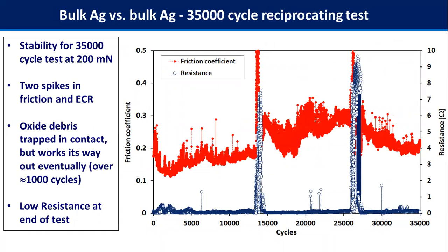So with bulk noble metals, these are much more resistant to sliding failure. And this is a test at much higher load now on a bulk silver alloy sliding against a bulk silver disc. And we can see here this instrumentation has the stability for a 35,000 cycle test. And in this particular test, you can see a couple of spikes in the friction and the contact resistance. And in these spikes, the oxide debris potentially, we speculate, is getting trapped in the contact, and it's gradually working its way out of the contact. But this is a slow process, and it maybe takes around 1,000 cycles to complete. But at the end, we're back to a low electrical contact resistance.